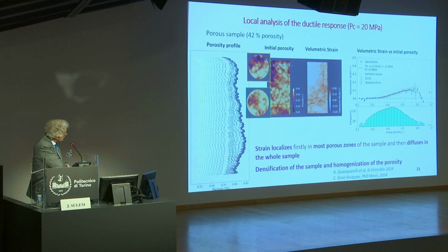And you see this evolution, and at some point, the whole graph is moving, translating, which corresponds to this uniform compaction. So we have strain which localizes first in the most porous zones, and then diffuses and fills the whole sample. And we have the densification of the sample and the homogenization of the porosity.